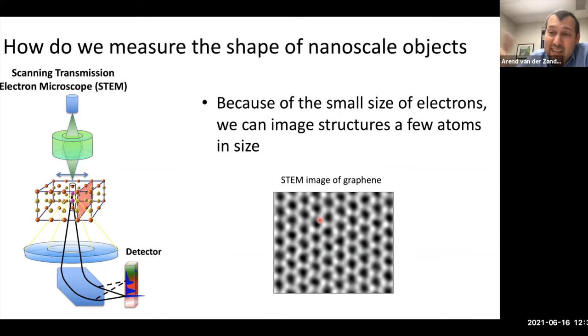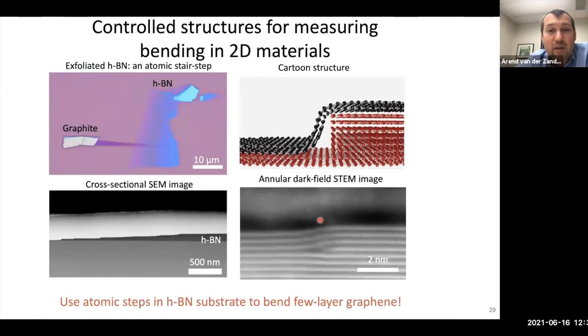But now a bend is actually on the side. So if we want to take an image of that, we can't look at it from the top. So in order to make these bends, what we did is we took graphite, few layer graphite or monolayer graphene, and we stuck it over the hBN steps. Here in this optical image, you can see this pink color is just a flat surface. And as we see these changes in color, those represent changes in thickness. So wherever you have a change in color, there's going to be a little step.